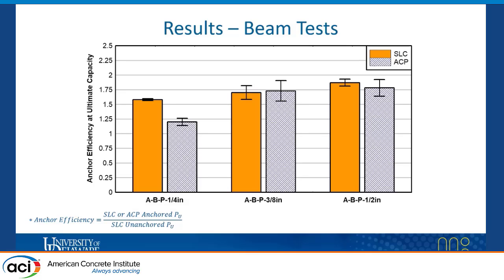And another way of looking at the susceptibility of the quarter-inch anchors following conditioning is by anchor efficiency, which is defined as the ultimate capacity of the anchored beams divided by the ultimate capacity of the SLC unanchored beams. As you can see from this, the quarter-inch group becomes less efficient in ultimate capacity compared to when it was unconditioned, whereas the 3/8 inch group and the half-inch group remained consistently efficient.